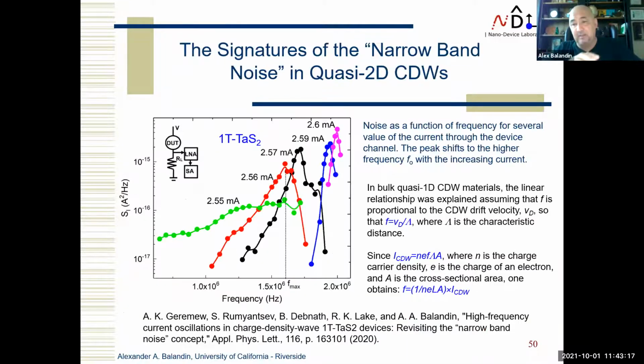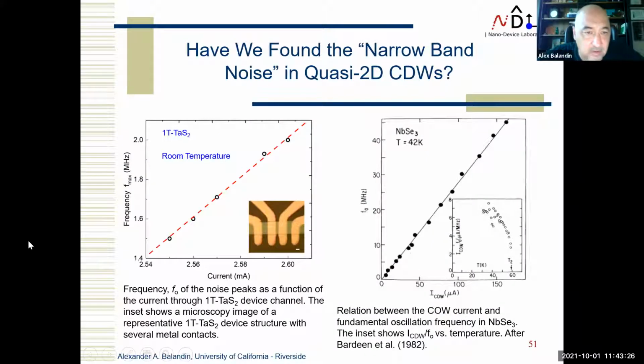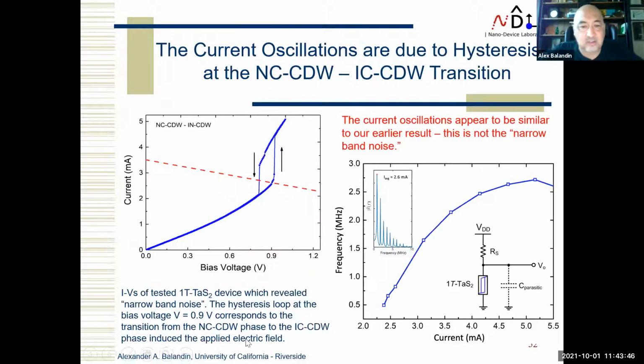At some point, we increased the frequency domain, and we saw, oh, we do see these peaks in the megahertz frequency range, like in older days. And moreover, the peak frequency increases linearly with the current. We thought, maybe that is exactly the same as what people observed for NbSe3 at low temperature, and we now have the same thing, functionality based on sliding of the wave, not just on hysteresis, because it looked very similar. But it turns out Roger Lake, a colleague of mine at Riverside, with calculations his student modeled, it turns out, no, we're just hitting on this device again, this hysteresis, and that's where oscillations come from.